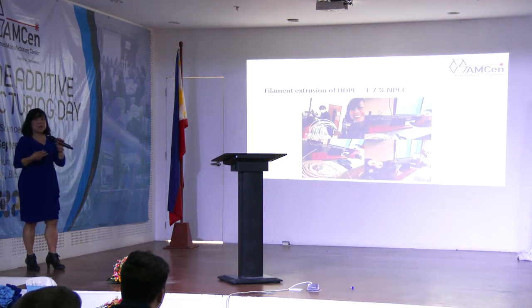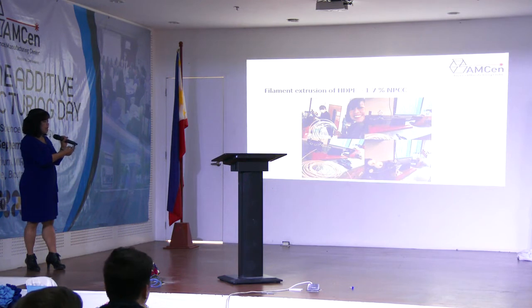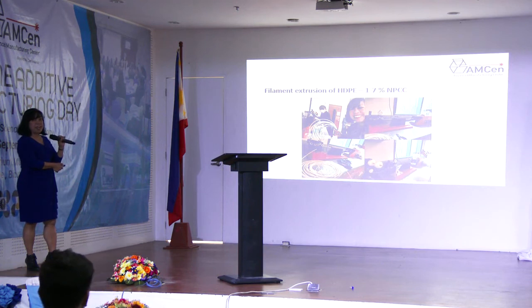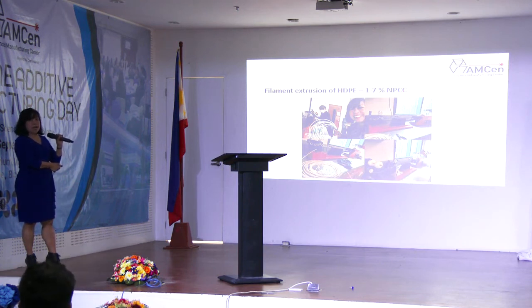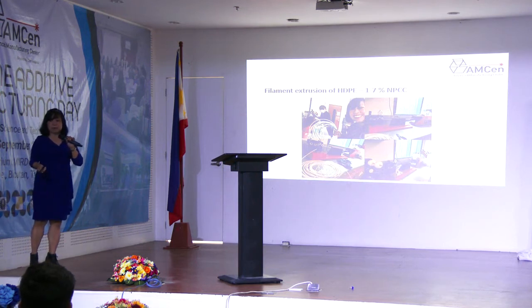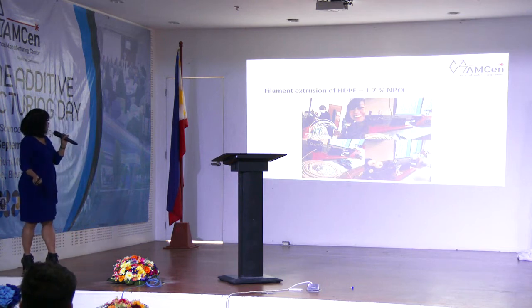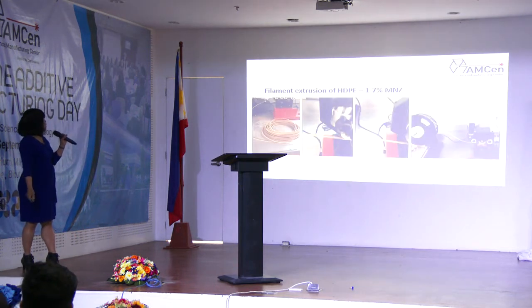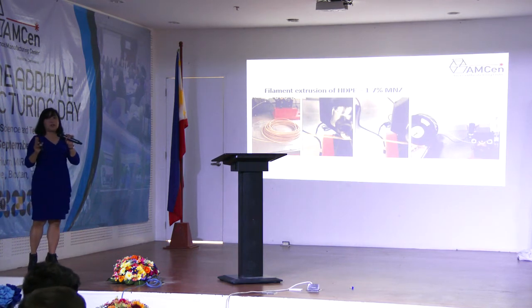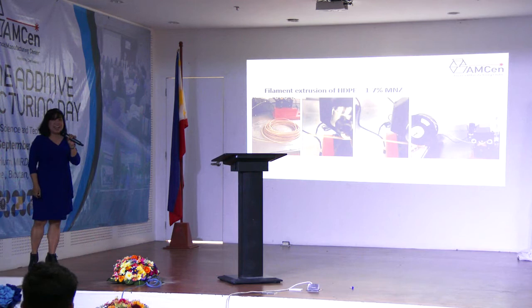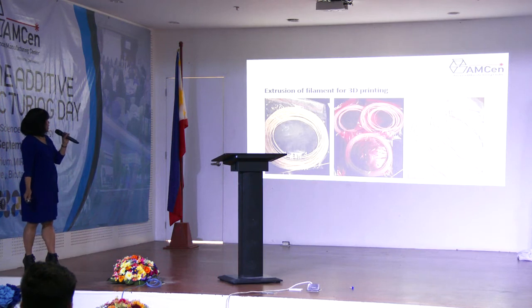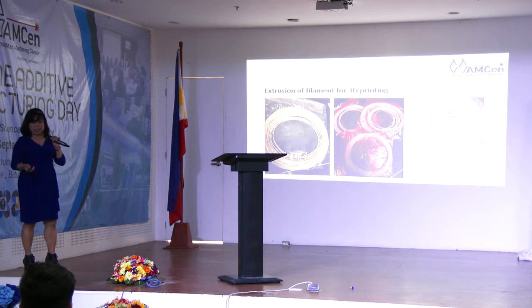Okay, so let's be working on the filaments. So we prepared 1 to 7% concentration of nanomaterial. In this case, we used the local nano-precipitated calcium carbonate. So we produce filaments for 3D printing. And, okay, we also use modified nanozeolite as an additive to produce nanocomposites. And these were the different extruded filaments ready for 3D printing.